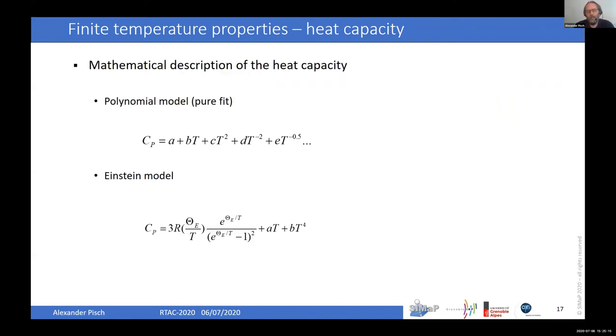So if I then have the heat capacity, I can either make a polynomial fit as it was done in the past, or what is more and more done in the Calphad community is use an Einstein model, where we have one Einstein temperature or multiple Einstein temperatures to fit the heat capacity. And it's clear that this is only valid at low temperatures. So if we want to go to high temperature, we need some extra terms in order to get good agreement with the experimental values.